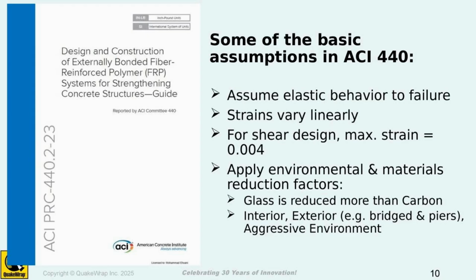Now, I mentioned before, there are codes like the ACI Committee 440 code for the design and construction of externally bonded FRP systems for strengthening of concrete structures. They have another one for masonry structures, and one for embedded, cast-in-place systems like rebar. But in this case, without going into the details, it's very similar to most of the other codes. You assume linear elastic behavior to failure, and strains vary linearly across the depth of your section. And for shear, they specify a lower strain of 0.004, which basically ensures that your cracks don't open too widely, so you take advantage of that aggregate interlock component of shear.